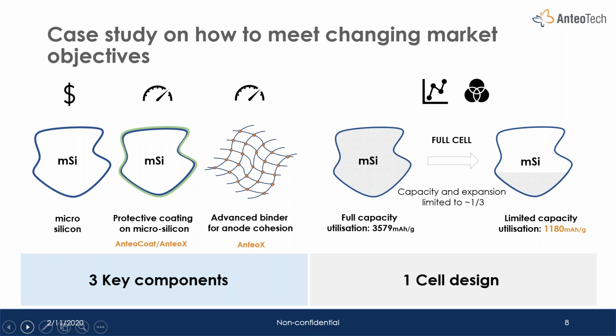Now, once you have created this anode containing the silicon active material with the protective coating and the binder, you can very easily transfer this anode into a conventional or commercial cell system against a metal oxide cathode. And the approach that can be used to help out this cell design further is to limit the capacity that you access from the microsilicon. So microsilicon at full lithiation, full capacity utilization, has a capacity of around 3,600 milliamp hours per gram. Now, if the anode is oversized and the cathode is undersized, you only access a fraction of the silicon, while still being able to access a substantial amount of capacity in the anode.